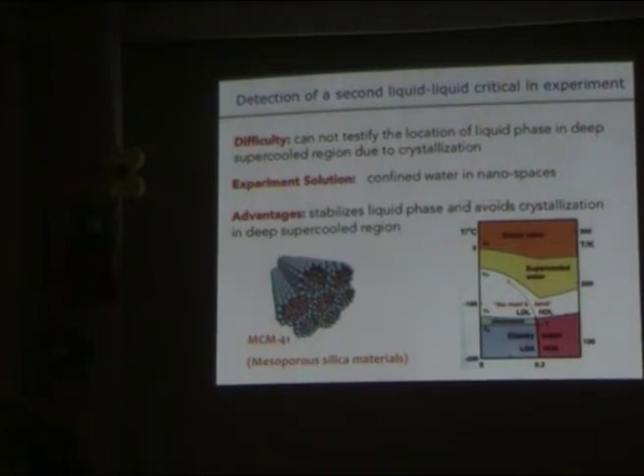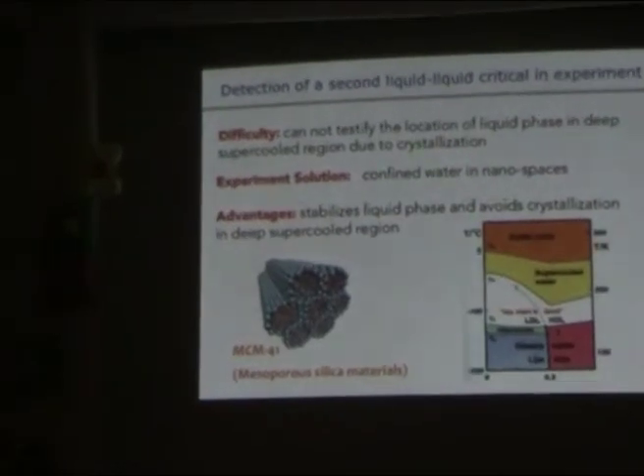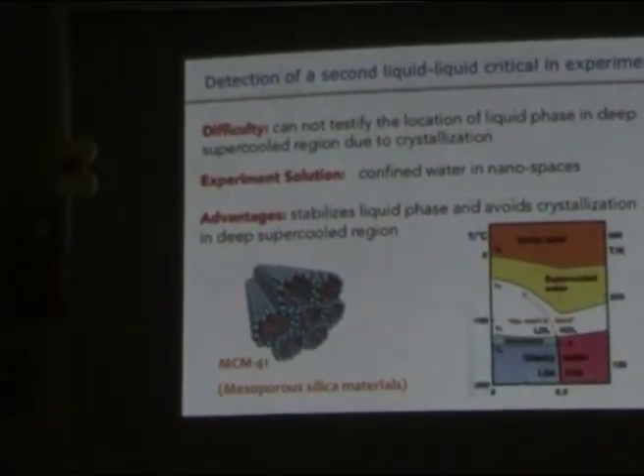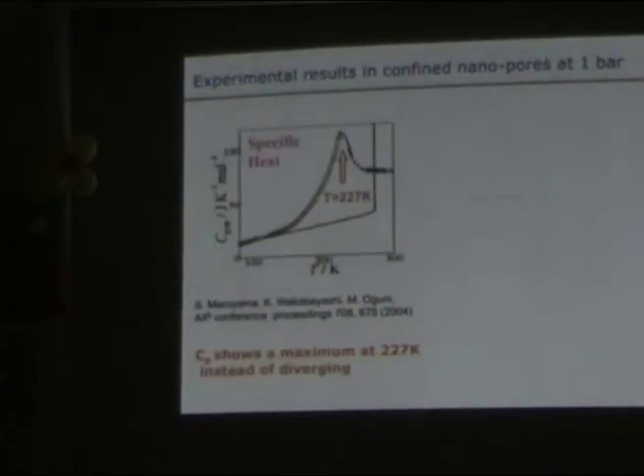So the experiment has some kind of solution. What they do is they confine the liquid into a nanostructure. We know that the lower limit at which you can access liquid water is 240 Kelvin in ambient conditions. But if you confine water in these nanogeometries, you can access a much lower temperature. It can still remain liquid. For instance, you can go down to 200 Kelvin and it can still be in the liquid phase. This is because the confinement effects of these nanogeometries stabilize the liquid phase and also avoid crystallization in such a system. So let's see what experiment gets by confining water in these nanogeometries.